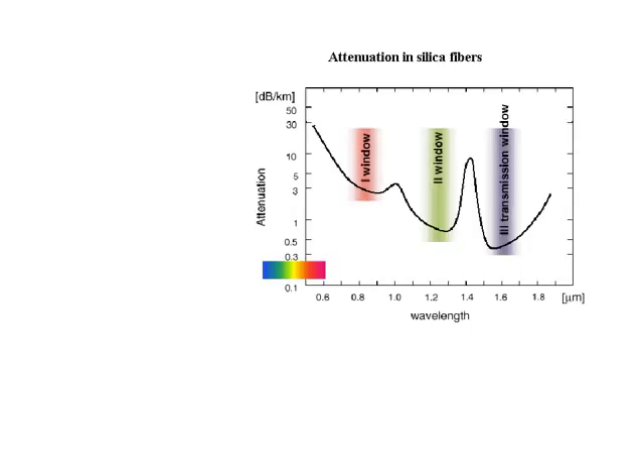This is the bottom of the spectrum. It shows the minimum occurring at 1.54 microns and indicated as the third telecom window, where, as we said before, the telecom signal runs. The spectrum also shows the second and first windows used before. First, second, and third windows tell us the historical evolution of telecom signals.